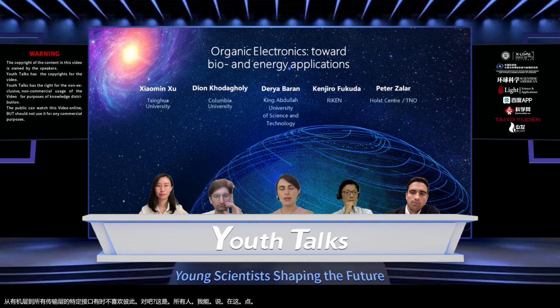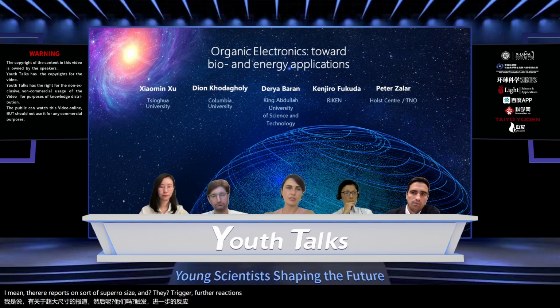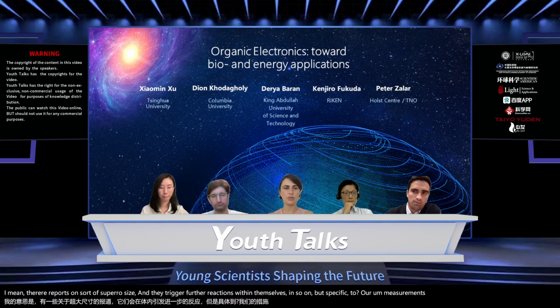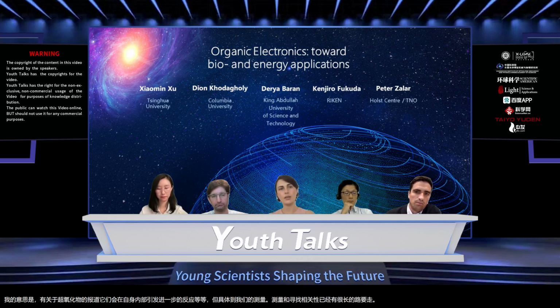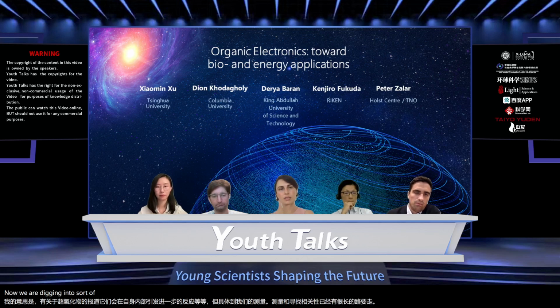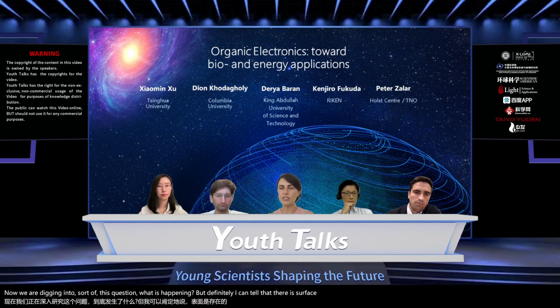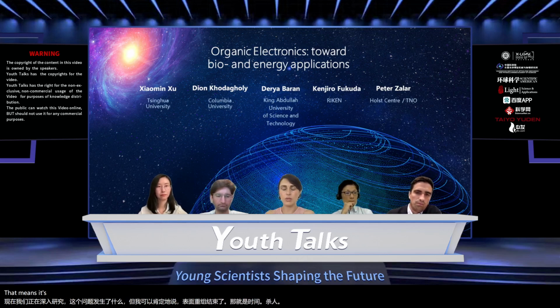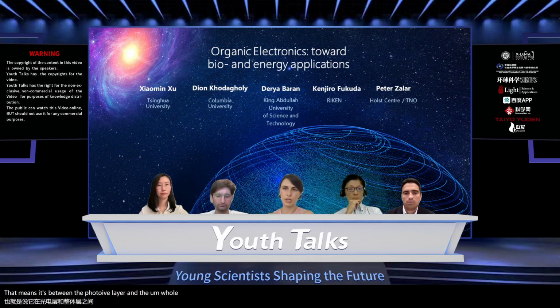I mean, there are reports on superoxides and how they trigger further reactions within themselves and so on. But specific to our measurements, it was already a long way to be able to measure and look into the correlations. Now we are digging into this question of what is happening. But definitely I can tell that there's surface recombination over time that is killing performance. That means it's between the photoactive layer and the hole transport layer in that case.